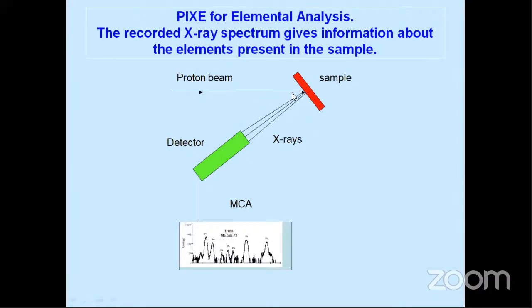So suppose you bombard a sample with a proton beam, then the X-rays will come onto the detector, and you can measure them. So you just put the sample, bombard it with the proton beam, then the emitted X-rays will be recorded, and you can get the spectrum. And each X-ray peak corresponds to a different element, and you can find which elements are present in the sample. So within 5 to 10 minutes, you can find the elements in the sample, and even at PPM level, very low element levels, which is difficult by chemical techniques. So the PIXE technique is very useful.